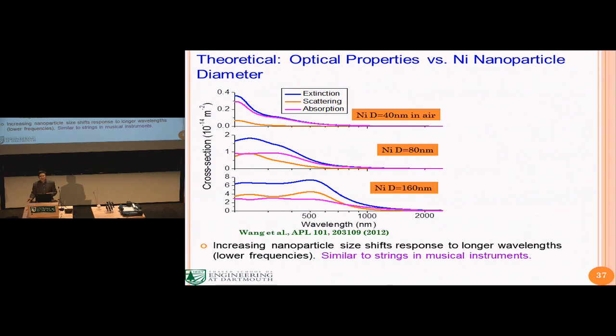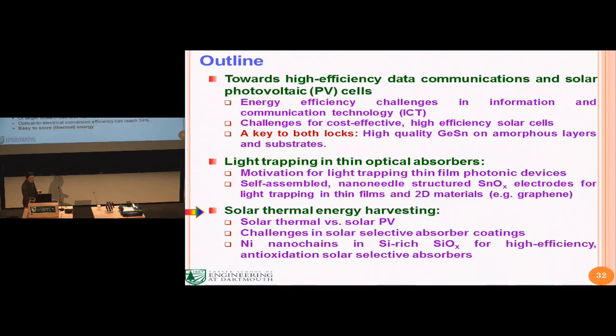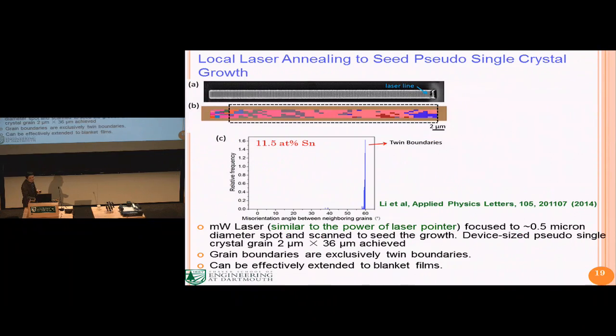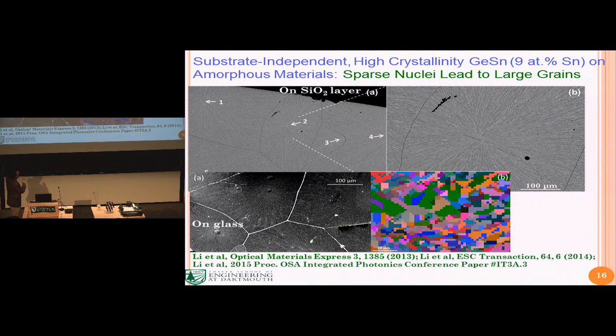What do you think is going on? We think it could be due to the undulations on the substrate surface. Whenever you have a small extrusion or something, that helps with the nucleation. So if you put it on glass or the polymer as you did, as opposed to the SiO2, equally largely spaced? Yes. I can go back to that figure. You can see the similar mechanism holds, and from this one to this one, the distance is about 0.3 millimeters or so. So the same mechanism holds. Same explanation, you think? I think it's possibly due to some irregularity on the surface, randomly.